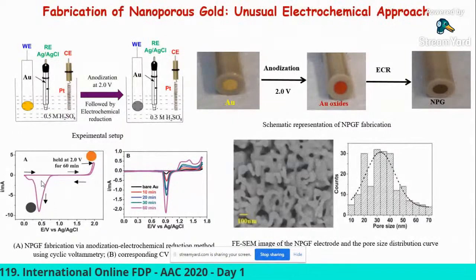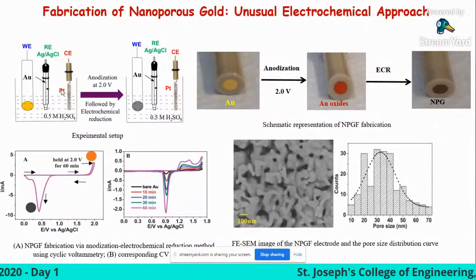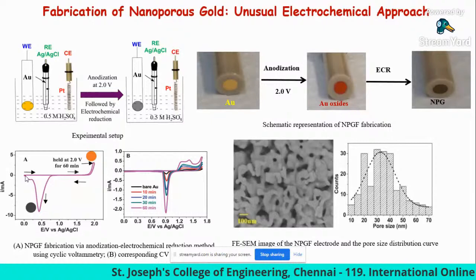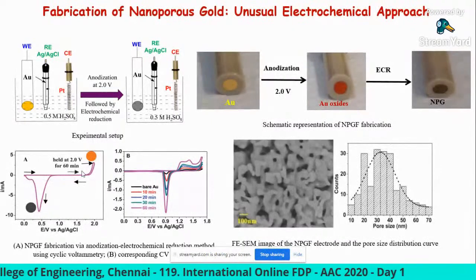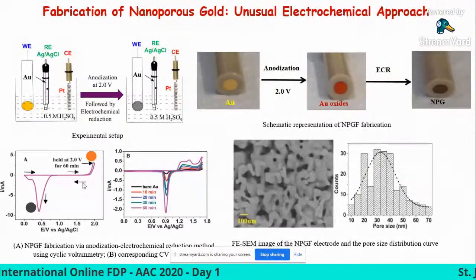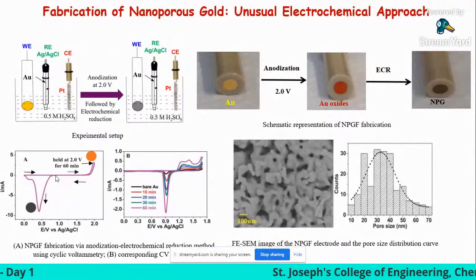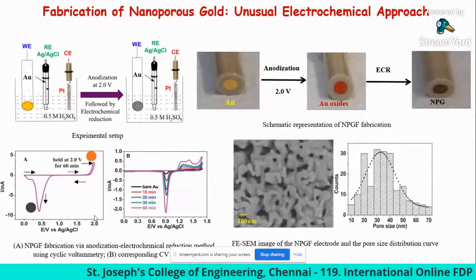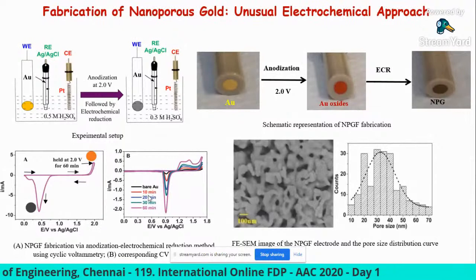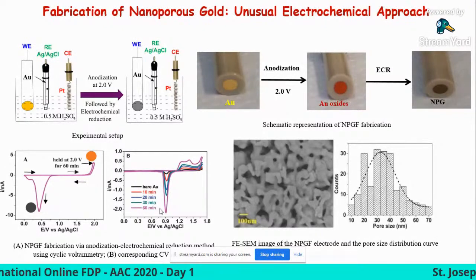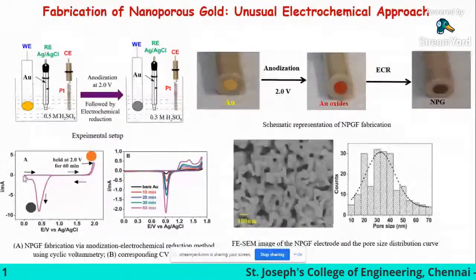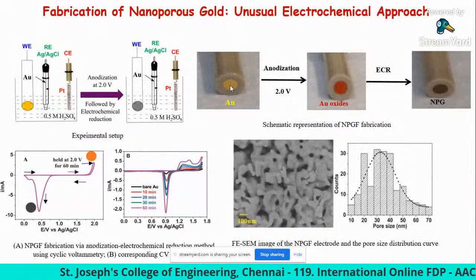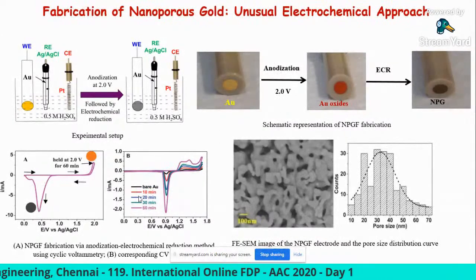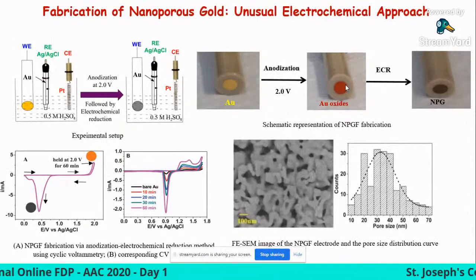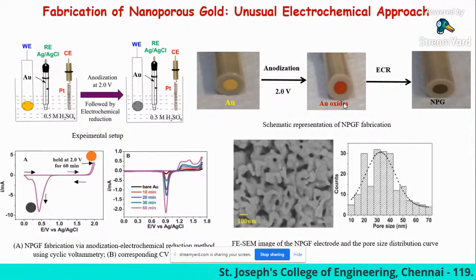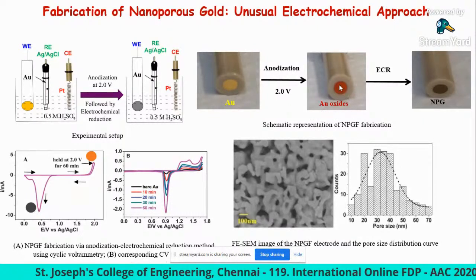Here you can see the cyclic voltammogram of the gold electrode in this experimental setup. We are varying the potential from 0 volt to 2.0 volt. This arrow indicates the forward scan, and this arrow indicates the backward scan. After the forward scan, we hold the potential at 2.0 volt for different times, for example 10 minutes, 20 minutes, 30 minutes, or even 60 minutes. During the forward scan, the Au electrode, which was initially yellow, changes after the anodization process from yellow to orange color. This orange color indicates the formation of Au oxide on the surface of the gold electrode.